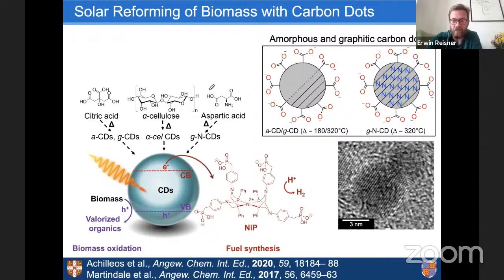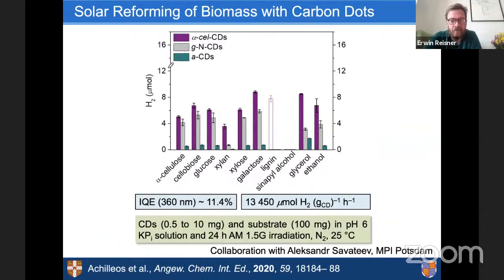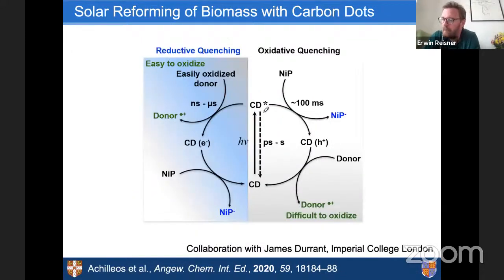And this is just how we make them. I've mentioned this before. And here's the bigger picture, and we can see now the hydrogen amounts versus substrates. You can see with the different particles or light absorbers, there's not too much difference anymore between soluble biomass and really insoluble biomass. There seems to be a really good interaction, after proper stirring, of this photocatalyst with the biomass that results in fairly decent yields. We're quite excited about this soluble form for photoreforming. As I think I do have time, I will just quickly summarize from a mechanistic point how this works.